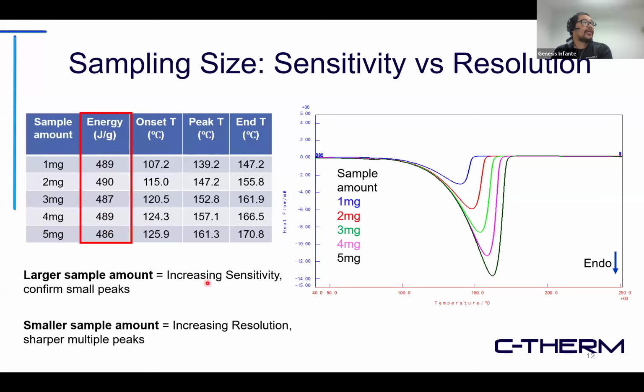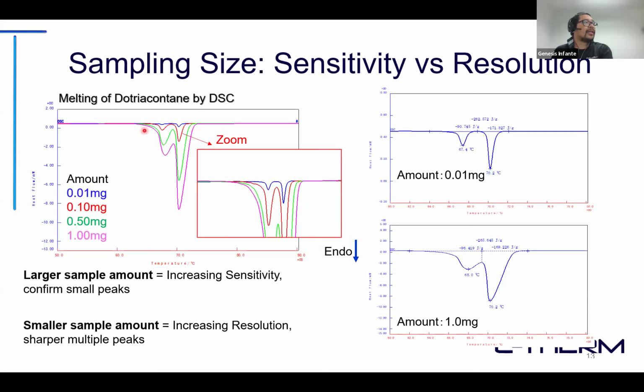So, something to keep in mind is that the sample amount can affect your sensitivity and resolution. If you're looking for increased sensitivity, you might want to consider a large sample amount. But if you have multiple peaks involved, you might want to increase the resolution. So for example, the melting of dotriacontane, which is typically used for lubrication, you can see that there are two distinct peaks right here.